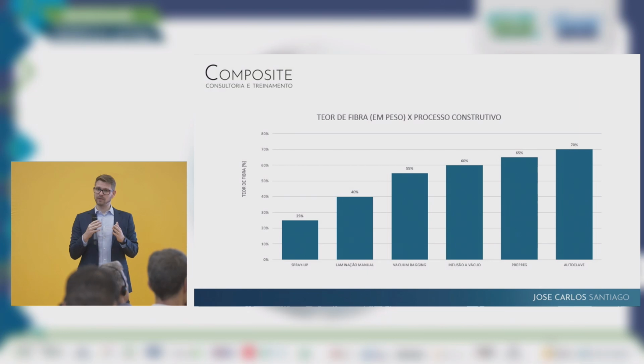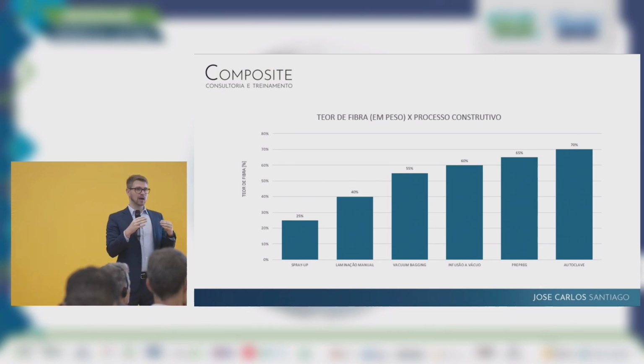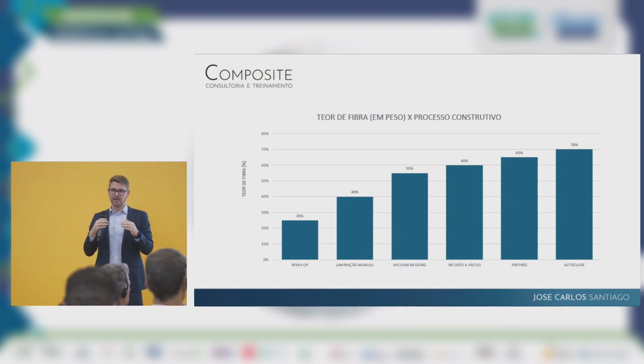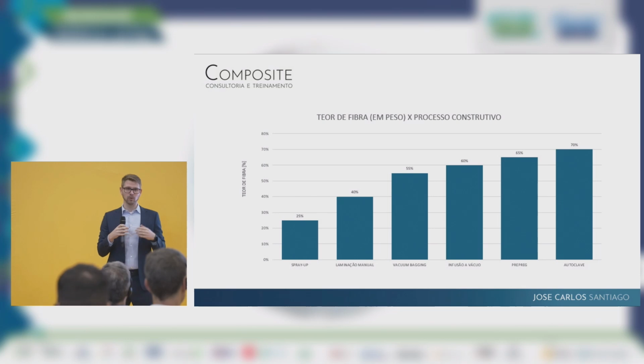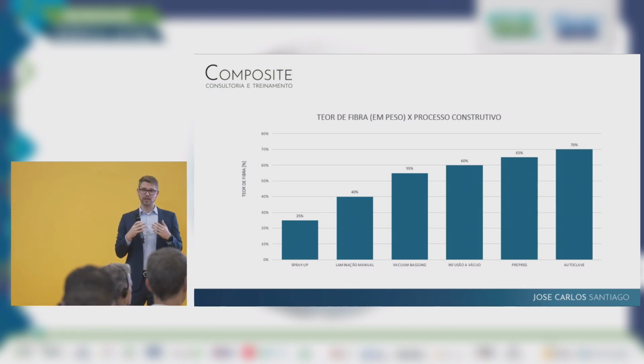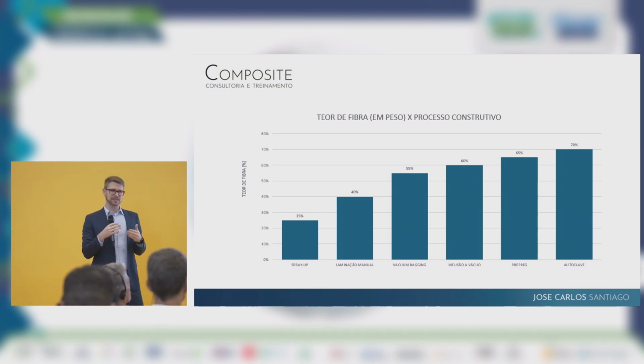We have vacuum infusion and vacuum bag, where you're going to have 55, 60% of fiber in the laminate. And we have more advanced processes like pre-preg and autoclave curing, where you put more temperature, more pressure, remove resin, and get more resistance. These two processes are more advanced.